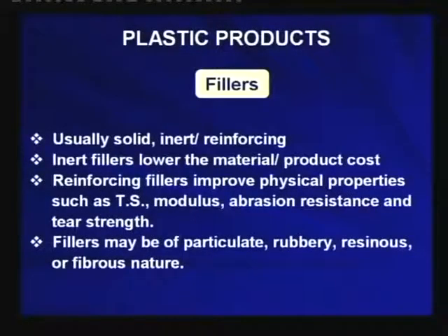So, inert fillers do not interact with the polymer chain, they simply remain present within the polymer matrix and reduce the cost by increasing the volume. It is known as inert filler. It will decrease the mechanical properties, it will decrease the tensile strength. It will increase the modulus of course, because the modulus is a low extension property. It will increase the modulus, but decrease the tensile strength, decrease the elongation at break, decrease the dynamic properties, and increase the hardness. This is the effect of filler.